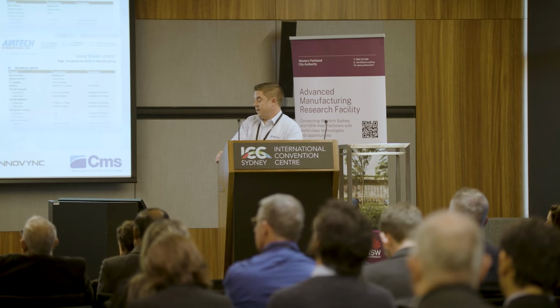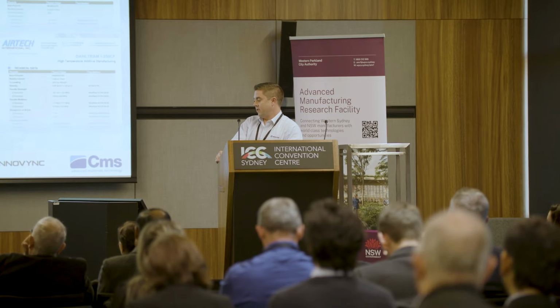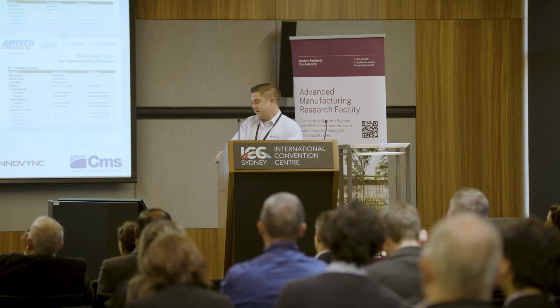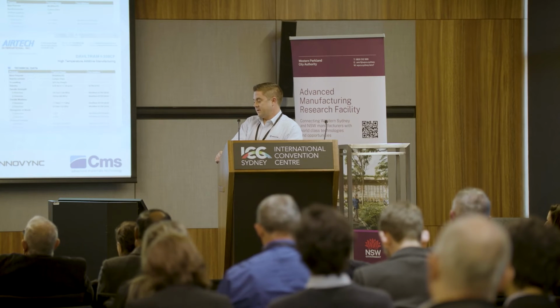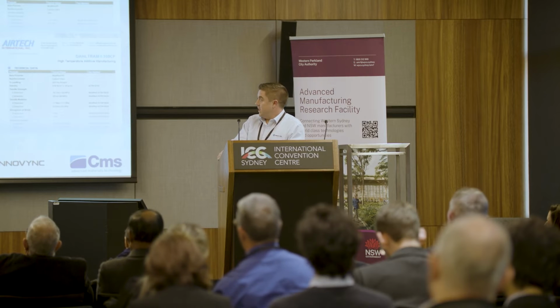The initial R&D was done using a polyamide reinforced with glass or carbon non-continuous fibres. CMS has since tested many other thermoplastic materials, and the materials used are similar to commercial thermoplastics used for injection moulding or extrusions. And they include PP, PESU, PET, PEI, ABS and Airtech Deltrum.